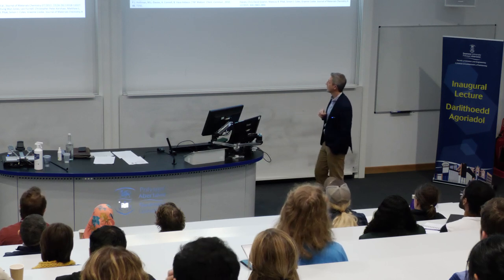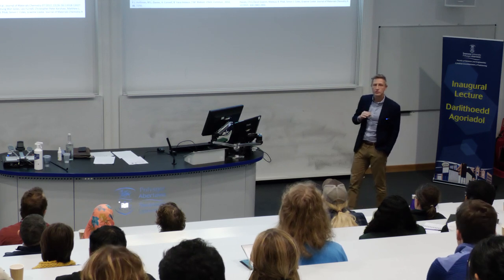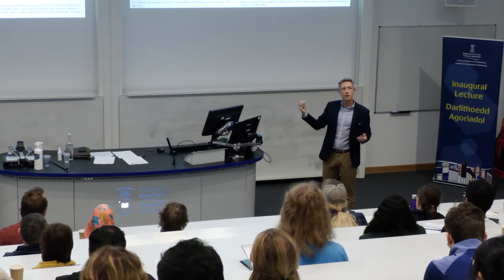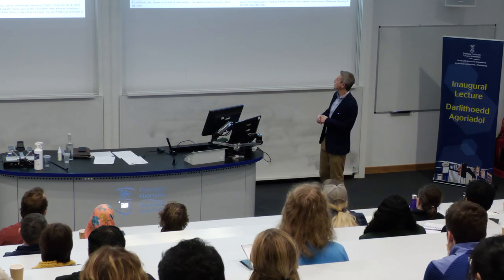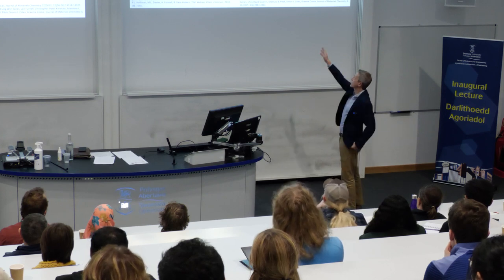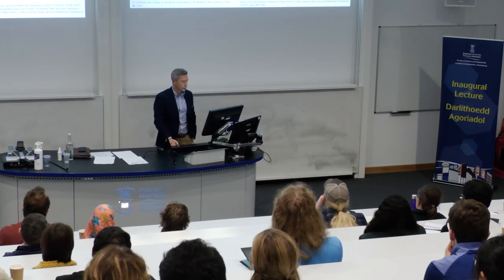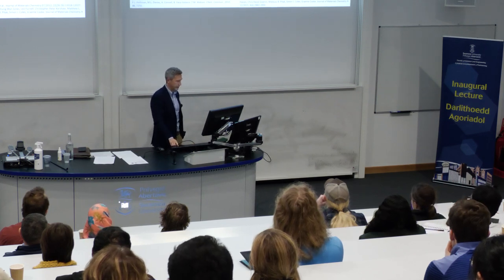The other part of my challenge and research at Bangor was to reduce the dyeing time. So the way you make these devices is you put an electrode in a dye solution, the dye sensitizes to the surface, you remove it after about 16 hours, and you can complete your manufacture. Of course, that's far too long if we're gonna manufacture these things at scale. So we came up with a way to dye them in just 5 minutes. And further, at room temperature. So we advanced the state of the art from 16 hours to 5 minutes.